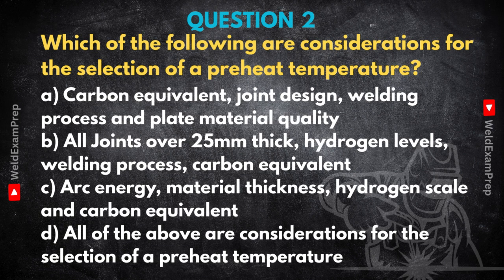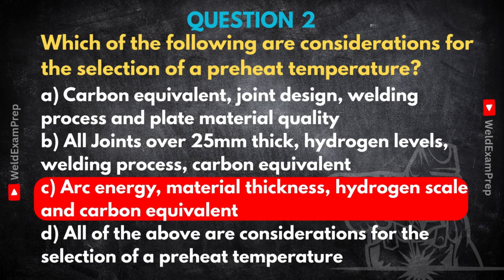Right. Option C. Arc energy, material thickness, hydrogen scale, and carbon equivalent is the most comprehensive and accurate list here. Let's break that down. Arc energy. That's your heat input, essentially. It directly affects how quickly things cool. Higher arc energy might mean less preheat needed sometimes, but it's a balance. Okay, material thickness. That seems obvious. Yeah, thicker materials just soak up heat much faster. They act like huge heat sinks, so they almost always need more preheat to keep that cooling rate slow enough. Makes sense. Hydrogen scale.